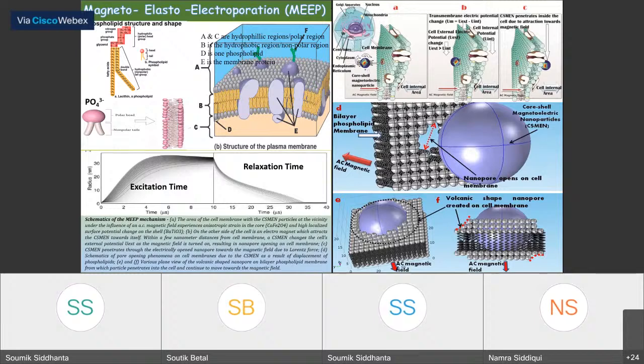The deflection of the phosphate head is the excitation time, which is polarizing the layer. The return of the phosphate head to its original position by the fatty acid chain is assumed as the relaxation time. Now, using our nanorobots, we can generate a pulse which is lower than the excitation time and greater than the relaxation time. This will result in a temporary opening of volcanic shaped nanopores on the cell membrane. These are temporary because the fatty acid chain will bring the molecules back to their position and close the nanopores.